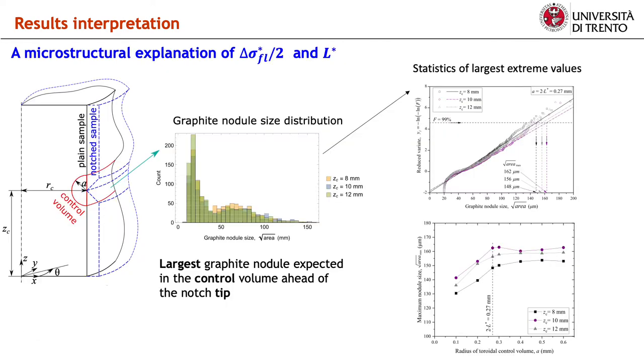From the fractographic analysis, it can be argued that the graphite nodules play a crucial role in dictating the notch fatigue strength of ductile cast iron. Since the fatigue process zone is concentrated in the vicinity of the notch tip, it seems reasonable to link the intrinsic fatigue strength to the fatigue strength corresponding to the largest graphite nodule expected in such critical volume, which is here taken as a toroidal volume centered on the notch tip and of size equal to twice the critical distance. Applying the statistics of largest extremes to the population of graphite nodules detected via CT scans, it is possible to evaluate a maximum square root area of such defect equal to about 150 microns.